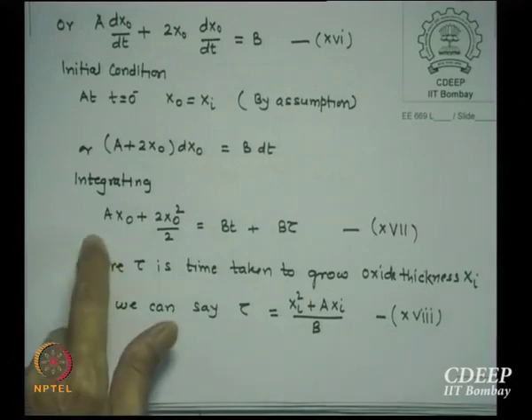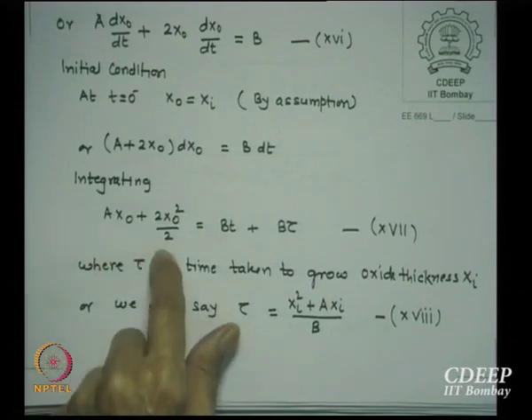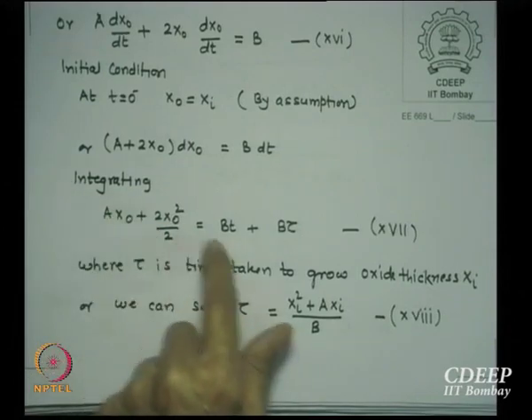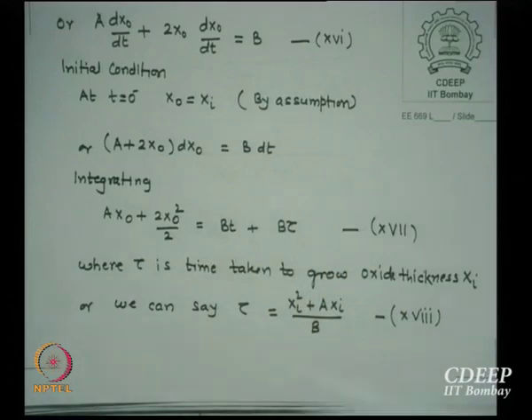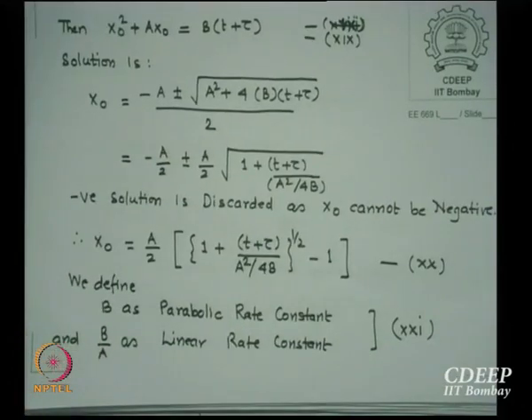I repeat, the term which I am getting is Ax0 + x0², is equal to B(t + tau). So this is the expression you will get: x0² + Ax0 = B(t + tau). For a thicker oxide growth, tau can be neglected. Why? Because t will be much larger than tau. Tau is very small, but it is existing. But for a thinner oxide, that may be comparable. So we must figure out how much is actually thin oxide during initial time. I'll show you how.